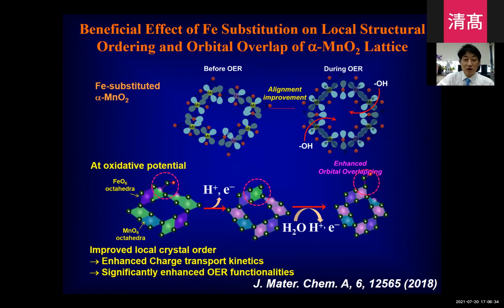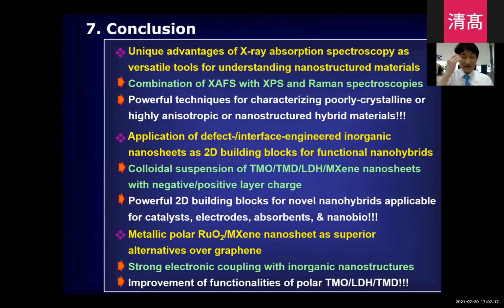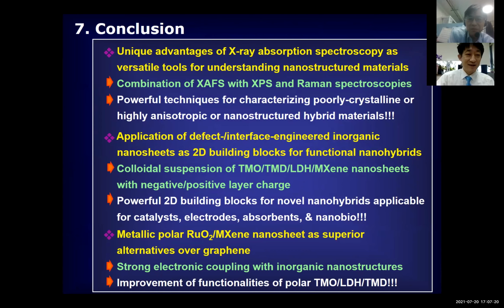So from that, we confirmed that during the OER process, in case of the iron substituted one, the collinearity of the MnO6 octahedra is improved. So it is definitely valuable to enhance the orbital overlap and the electrocatalytic activity. Also, it is valuable to improve the mass transfer properties. So it is confirmed by the impedance analysis. Based on that, we can suggest such an operation model for the beneficial effect of the iron substitution of the alpha MnO2. My talk is a little bit long, but anyway, let me conclude.